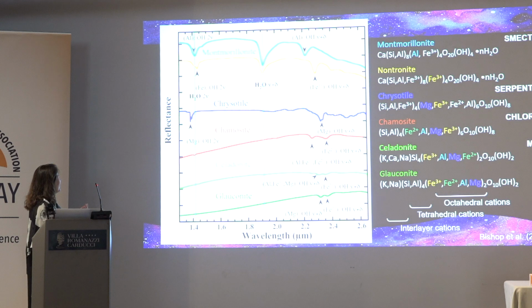So one of the things that's important for Mars or other planets when we're trying to detect different types of phyllosilicates is looking at the position of these OH bands in the octahedral sites, connected to the cations in the octahedral sites. So if we look at montmorillonite and nontronite, for example, we see this difference in the peak positions, and saponite or hectorite would be slightly longer wavelength than the iron. And if we look at serpentines like chrysotile, we see a magnesium OH band, and in chamosite we have iron 2+, and also a combination of aluminum and various iron. And micas also have multiple cations, and that gives you multiple bands in this region.